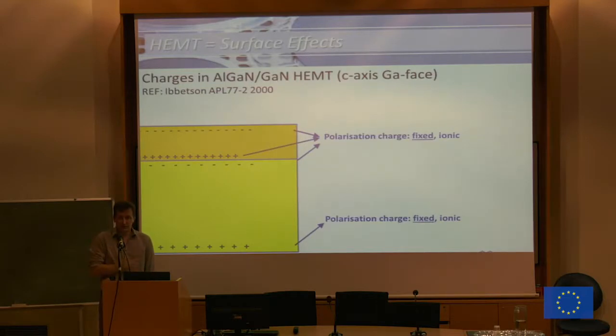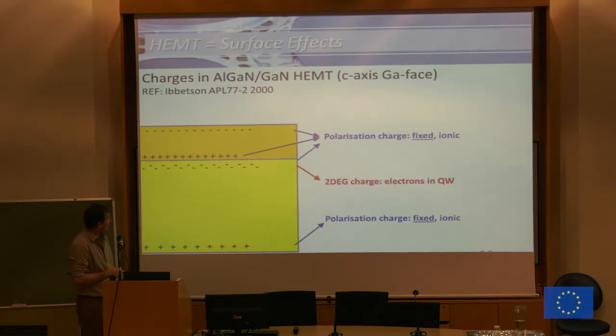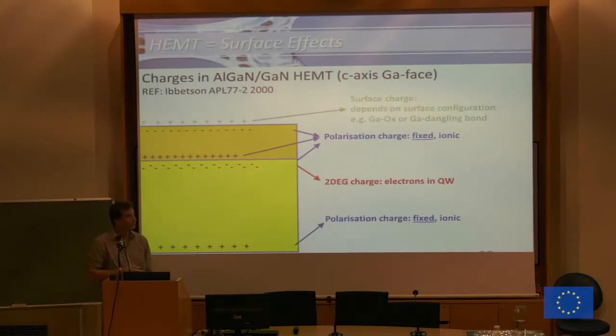But these charges you cannot use in your transistor, because these are ionic charges. They are fixed to the crystal. They will not move. So in order to create mobile electrons that will be attracted there in this quantum well because of the configuration with the band gap, and because you have higher positive ionic charge here than there, these electrons need to come from somewhere, and you need to have, in fact, charge neutrality across the whole structure.